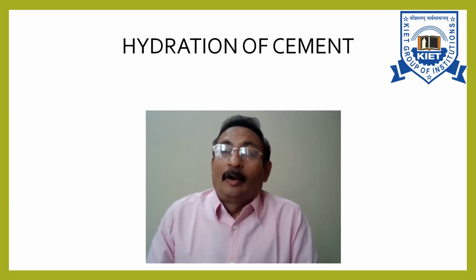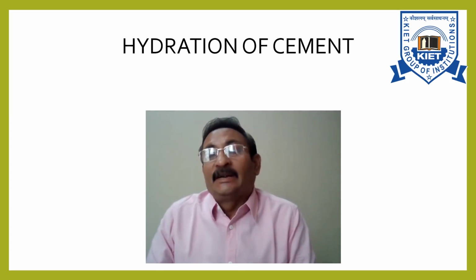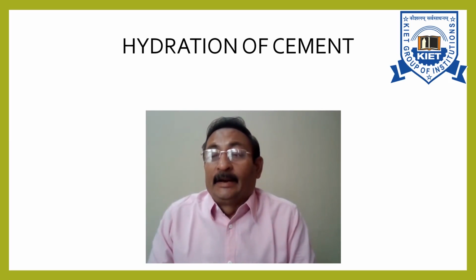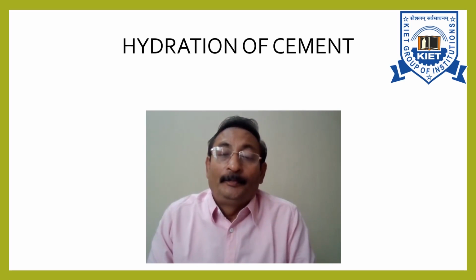Welcome to this video lecture on hydration of cement. In the last video lecture, we were discussing Bogue's compounds, which form due to the fusion in the kiln. Tricalcium silicate and dicalcium silicate are the most important compounds because they are responsible for strength. Together, they constitute 70 to 80% of the cement.